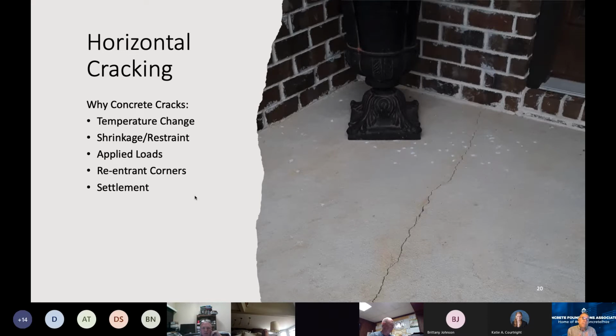So when we talk about modulus of rupture being 10% of its compressive strength, if you add up the stress that's created by that element trying to shrink, you can calculate exactly where a crack is likely to occur based on what the modulus of rupture is applied to the cross-sectional thickness of that slab. And I've done that numerous times on sidewalks and driveways. Looked at an unjointed slab, with no construction joints or no control joints put into them, and been able to go out and predict where those cracks are going to occur. Now, they also may come from settlement, but here we've got no displacement on the two sides of the crack, which is a clean indication of a shrinkage crack.